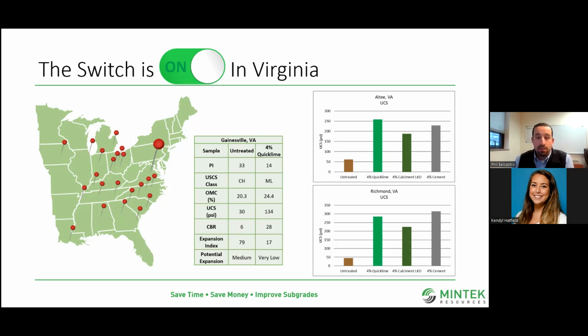In Gainesville, just west of DC, this developer was not only looking to increase the unconfined compressive strength and the CBR, but he also wanted to mitigate swell as well. So we benefited from that soil modification, not just stabilization to get the strength. We mitigated that swell potential, taking it from a medium threat to a very low threat of expansion. Did that testing here at the Innovation Center with an ASTM test. So it's pretty good to see those results. So soil stabilization with the unconfined compressive strength, but also the expansion mitigation as well.